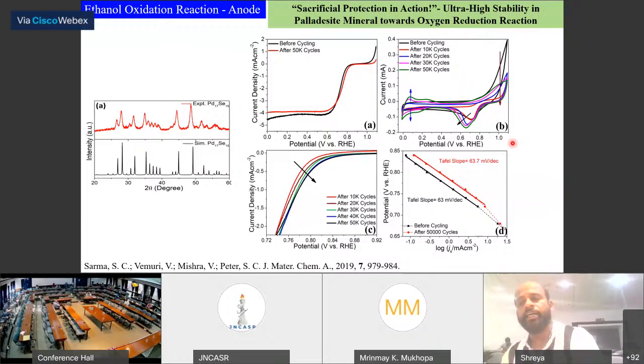Here, what we noticed is that up to 50K cycles, we took a CV every 10K cycles, and you can see that selenium oxide formation is happening. There is a shift for both the forward and backward scans in the CV cycle. Upon cycling, the activity slightly improves and then keeps the stability as good, and this mechanism is similar to platinum, and the Tafel slope is close to platinum-like activity.